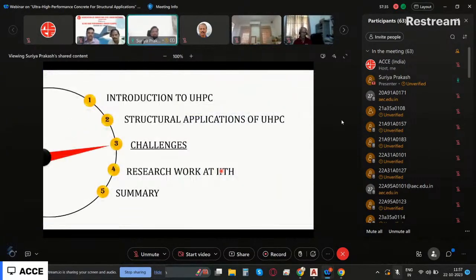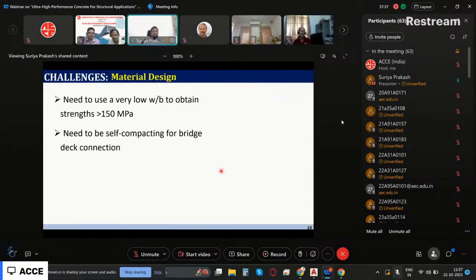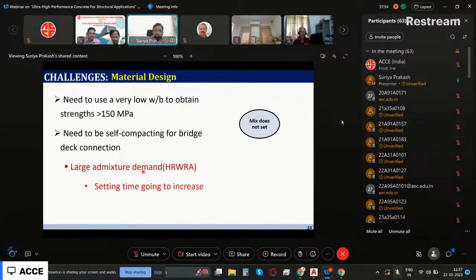And okay, so now let's see what are the challenges. Okay, so we need to use very low water to binder ratio to attain strength more than 150 megapascal, and we need to be self-compacting for bridge deck connections or other things. So when you want it to be self-compacting, you need to put a lot of admixtures, and setting time is going to increase. So the mix will not set.